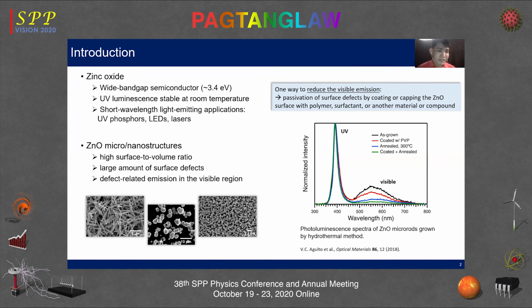And furthermore, ZnO micro-to-nanostructures have many chemisorption sites where environmental molecular species can be adsorbed, and this may lead to material or device degradation. By coating or capping the surface with a surfactant or another material or compound, the surface defects can be passivated and the ZnO surface can be prevented from interacting with unwanted molecular species from the environment, and as a result, the photoluminescence can be improved.